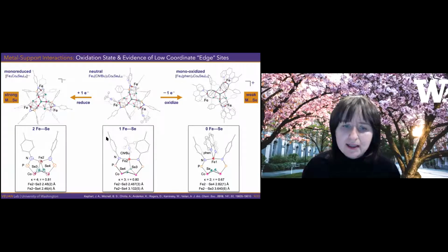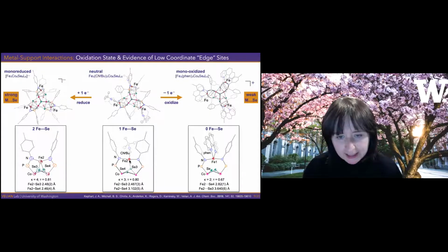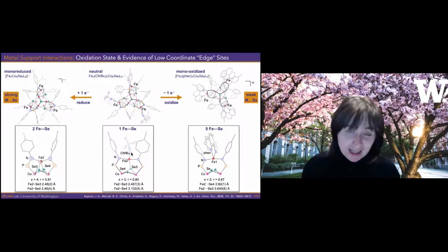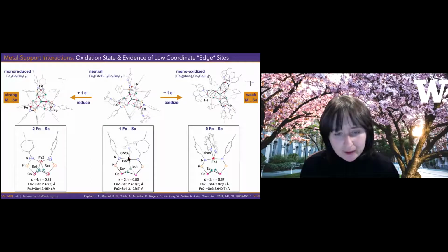And let's take a quick look at what the edge site looks like, the connectivity there. So here's one iron site. It's coordinated in this case to an isocyanide. In fact, the stretching frequency of the cyanide group tells us that the iron is extremely electron deficient. And if we look here, so the iron is anchored to the cluster surface. I'm only showing 2 cobalt atoms and 2 seleniums for simplicity.